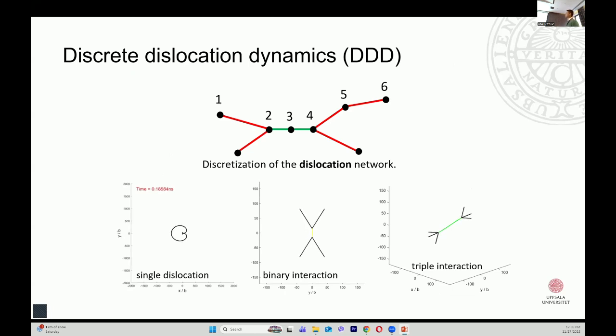So in order to really dig into the interactions between hydrogen and dislocations and visualize the interaction, here I would like to try to sell to you an approach which is called discrete dislocation dynamics. In this approach, we discretize dislocation lines into straight segments so that we get a bunch of nodes. And in each time increment, we can evaluate the nodal velocity of each node so that we can capture the entire evolution of the dislocation structure. And with this approach, it is possible to simulate some elementary processes of dislocations, such as the operation of a Frank-Read source, formation of dislocation junctions.